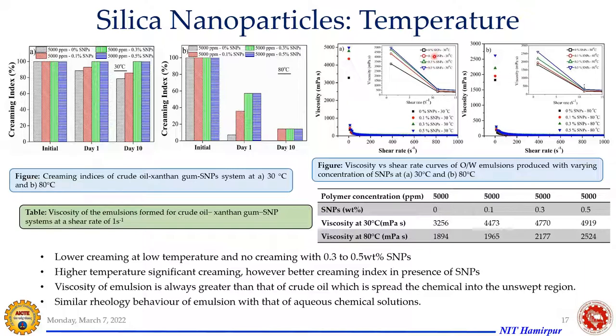Okay. So we have also seen the rheological properties. You can see at different nanoparticle weight concentrations how the viscosity was enhanced at different shear rates. So the improvement in the viscosity was seen here with the addition of nanoparticles. And this is the condition with polymer, where you can see the viscosity obtained at different temperatures, and how the viscosity was changing with these nanoparticles. So this gives an idea about the rheological property.